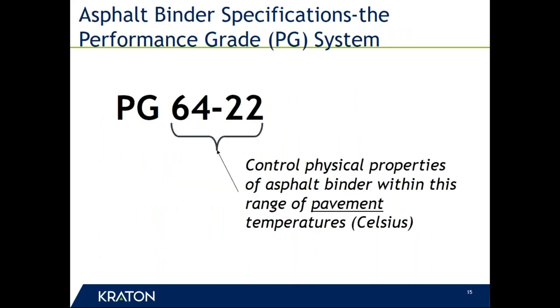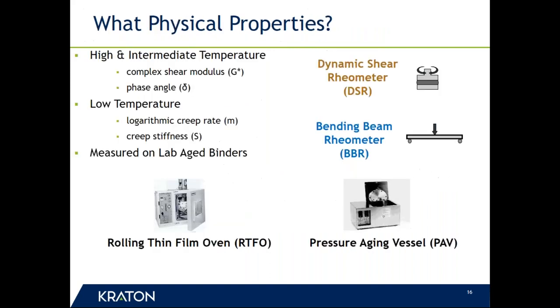When you see a number like 64 minus 22, what that tells you is that's the range of pavement temperatures over which your binder is expected to perform adequately. That is, it should be able to resist rutting and should be able to resist fatigue cracking over that range of temperatures for typical highway applications in terms of moving traffic and that sort of thing. Those numbers, by the way, are temperatures in degrees Celsius. 64 is about 147 Fahrenheit, and minus 22 is close to minus 8 Fahrenheit.